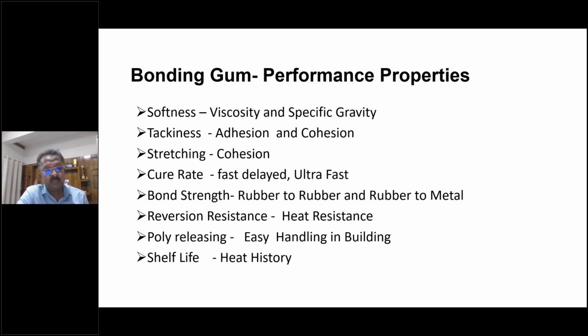Cure rate, we have to control. Bond strength. Should have very good bond strength between rubber to rubber and rubber to metal. Heat resistance. While the tire is running in most applications, the bonding has to have very good resistance to the heat. Otherwise, it will separate. Poly releasing. While applying, the bonding should easily come off the poly. Heat history, shelf life. The bonding has to be kept for 3 months, sometimes 4 months before using. So it needs a very good shelf life. The heat history should be very good.